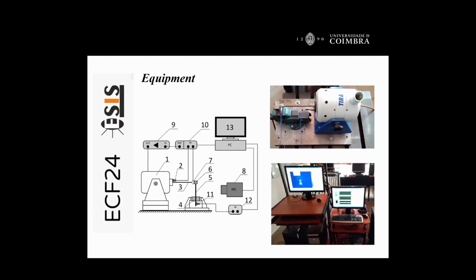The system used to produce the fatigue load is shown here, and we can observe an equipment based on a shaker, number 1, that produces the oscillation, and the specimen is number 5. This shaker produced the loading in controlled displacement, and you can capture by thermography the map of temperature in the sample, and you can also obtain the displacement and consequently the load, the force that is applied to the sample. Simultaneously, we also apply an acoustic emission system in order to analyze the acoustic emission produced during the fatigue tests on the sample.